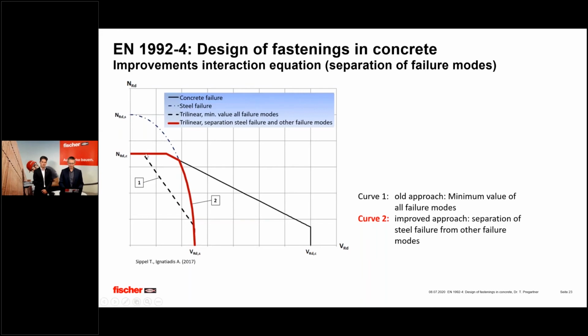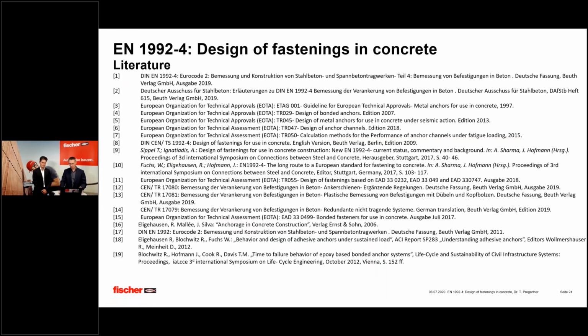Now the final design proof is then the combination of the two, which gives you this red line, which is called curve 2, which gives you finally the function of the utilization degree. And you see already that the area in between the lines 2 and 1 you gain if you work according to EN 1992-4 in terms of additional performance.